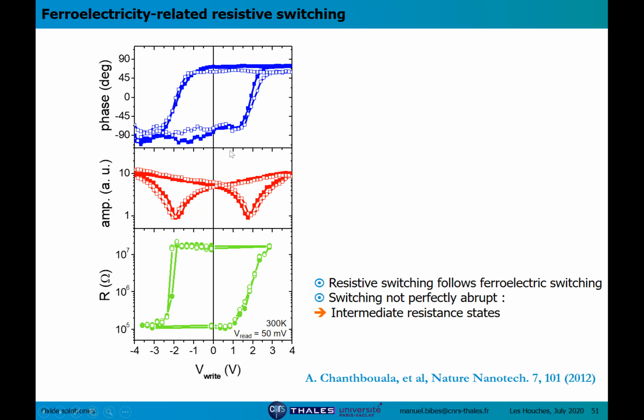So this is again the piezoelectric loops, and here you can see the resistance loop. Here that's the resistance measured at low voltage as a function of the amplitude of the pulses that we applied before reading to set the junction in a given ferroelectric state. What is interesting is that we have these 2 orders of magnitude resistance change, but you can also see that we have intermediate resistance states as well.